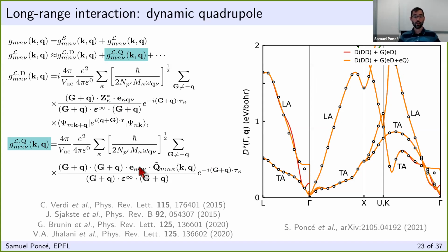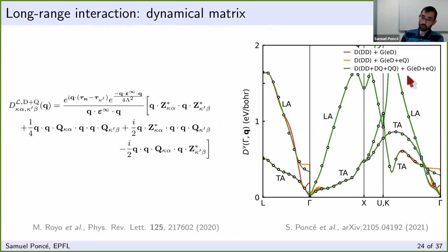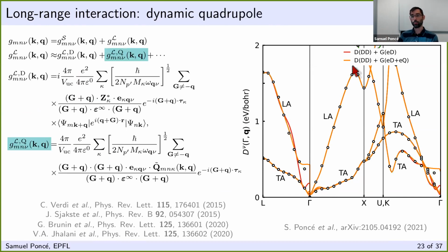The reason for this is that we have here this eigendisplacement vector. So it's really important to also add this quadrupole at the dynamical matrix level, because then when you diagonalize it, you will obtain the eigendisplacement vectors. If you don't include them, as is done here in orange, then those eigendisplacement vectors are not correct and you get those spurious interpolations. However, if you include it also at the level of the dynamical matrix, which was done in this paper, then you have a dipole-dipole term, a dipole-quadrupole term, and a quadrupole-quadrupole term. If you do that when you do the subtraction and addition back, then you finally obtain a good interpolation, which is this green line. We correctly go to a finite value here, and then we go to a different value as we approach gamma from a different direction. This can be done in EPW using this quadrupole file that we have to provide to EPW.